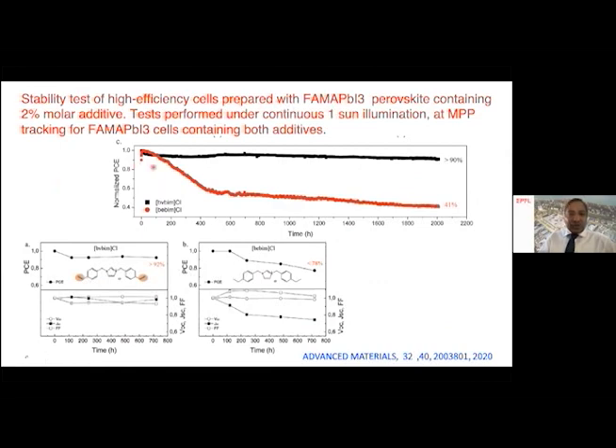So here is the stability data. That's with a functionalized ionic liquid, with polymerizable groups. After 2000 hours, the decrease in efficiency is less than 10%. Without this ionic liquid, the decrease in efficiency is almost 60%, so the remaining efficiency was only 41%. You can see the beauty of this ionic liquid forming a polymerizable shell on the top of perovskite grains.